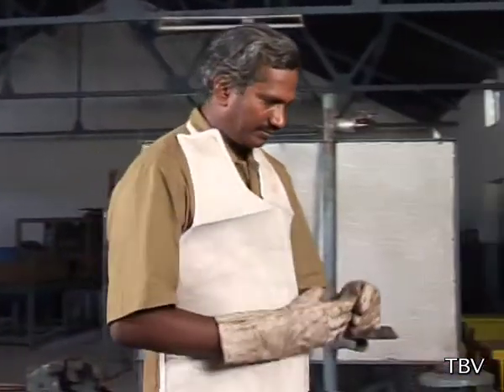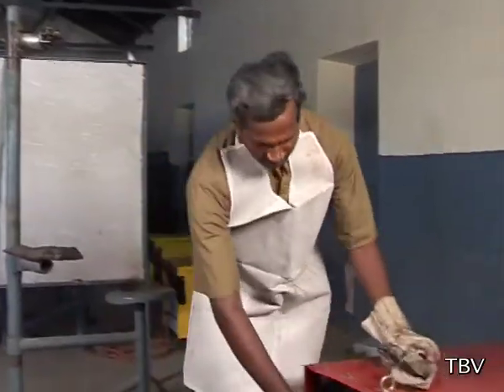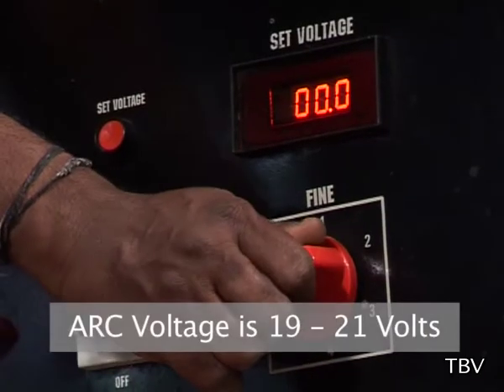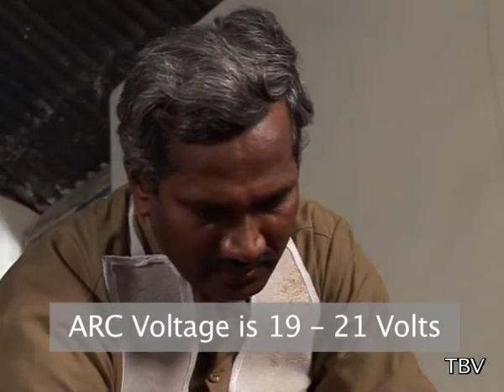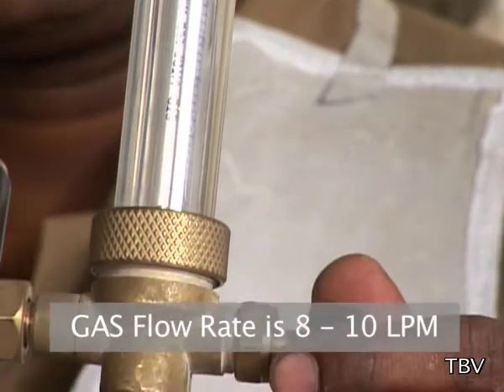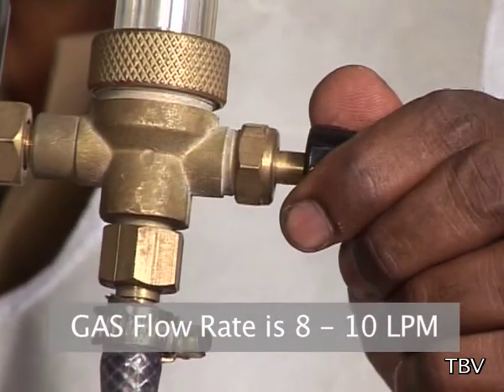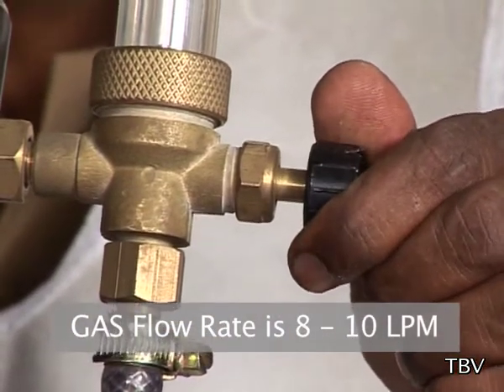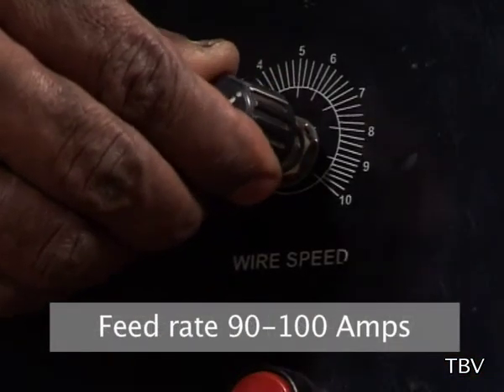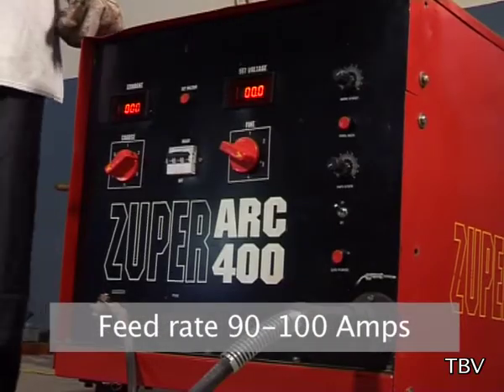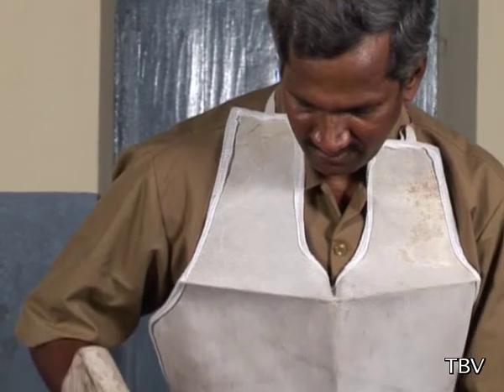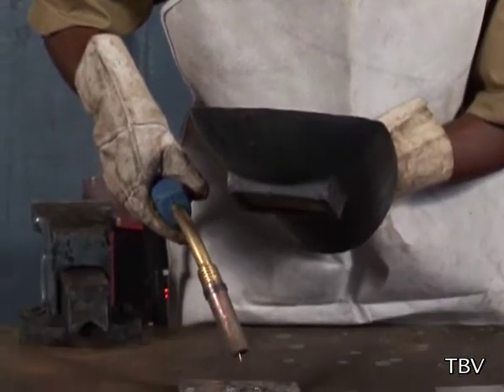By now, the CO2 gas is also ready. Set the arc voltage at 19 to 21 volts as required for dip transfer mode. The gas flow rate is set at 8 to 10 LPM. Set the feed rate so as to get 90 to 100 amps by striking the arc on a scrap plate.